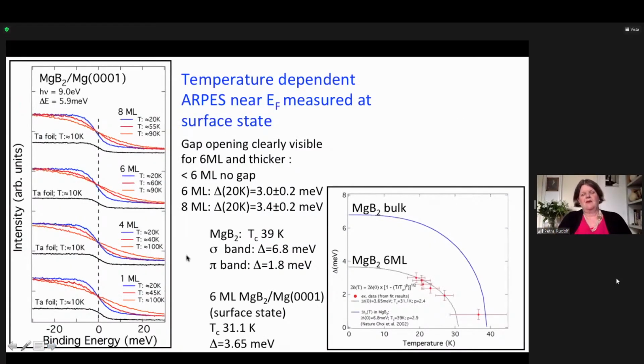Well, that is something that we studied with angle resolved photoemission. Here we are looking at the density of states around the Fermi level. And what we did was always to measure a real metal which does not go superconducting, namely tantalum, with it. So when you have just one layer of magnesium diboride and you measure it together with the tantalum, you see that in both cases, all the line goes through the Fermi level. So this doesn't have a gap. We are growing it on magnesium.